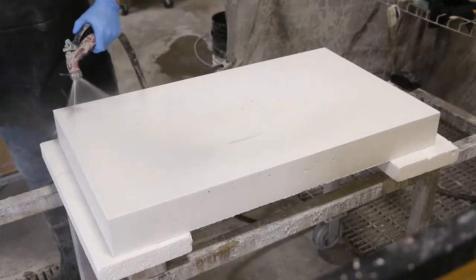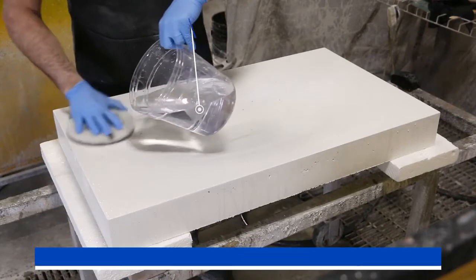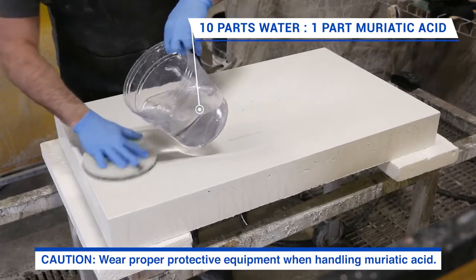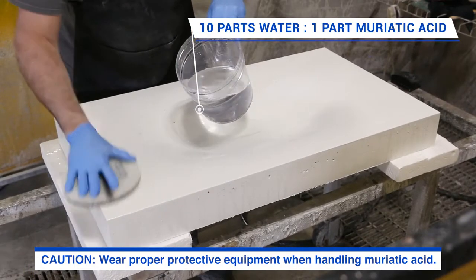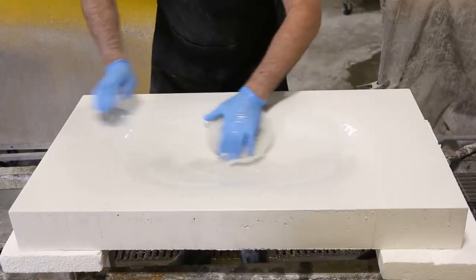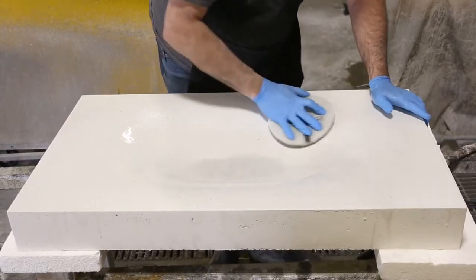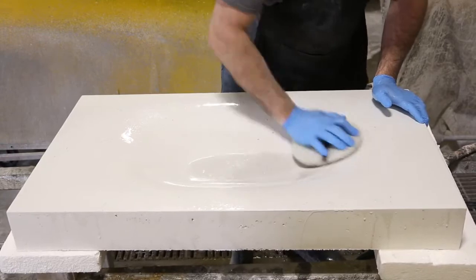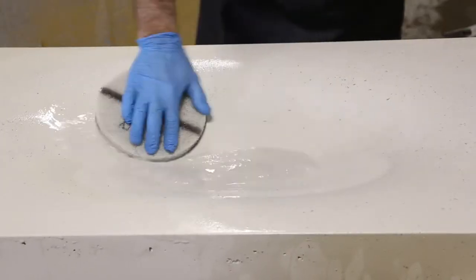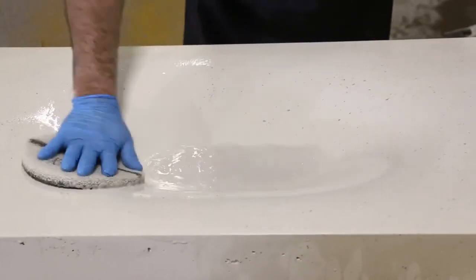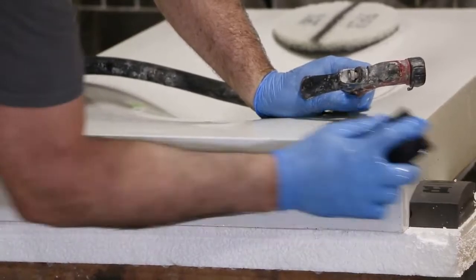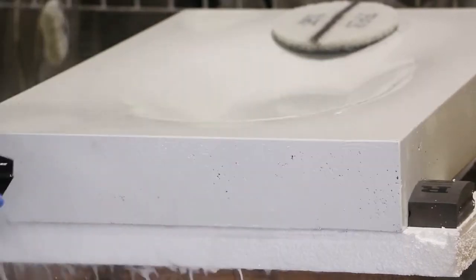Wet the piece and, using a 10:1 dilute solution of muriatic acid, gently scrub the cream from the surface, exposing the sand and fines beneath. Continue this process until the exposure of black sand has been achieved. Diamond sanding blocks may be necessary for the sides.